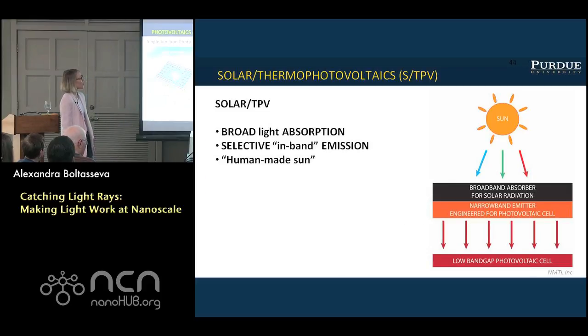So a much better approach would be to design a specific absorber which takes the broadest spectrum of light you have and absorbs it all. We can do it in optics with matte surfaces, but the problem is that when you absorb that much light, you're just heating things up. That's the most efficient way of doing that. So you heat things up to a very high temperature, and then you re-emit it in a very special way to match with the PV cell.